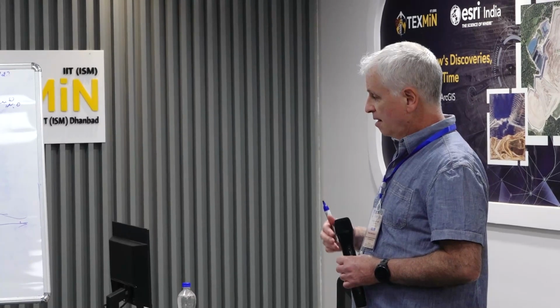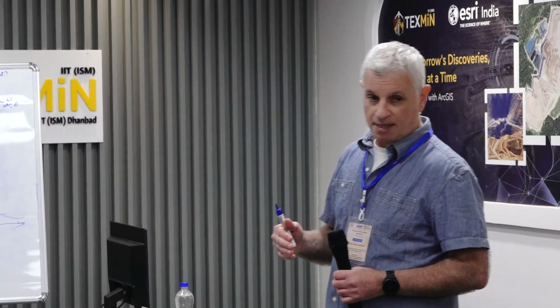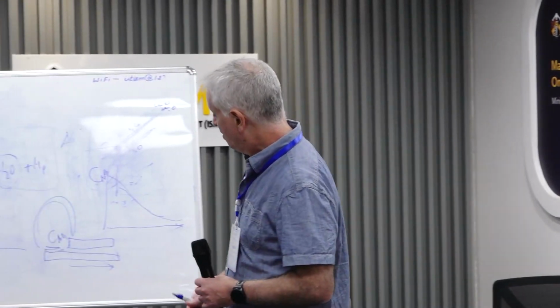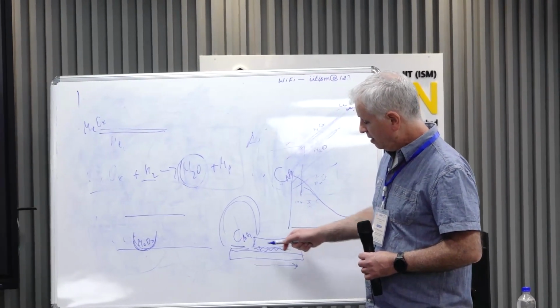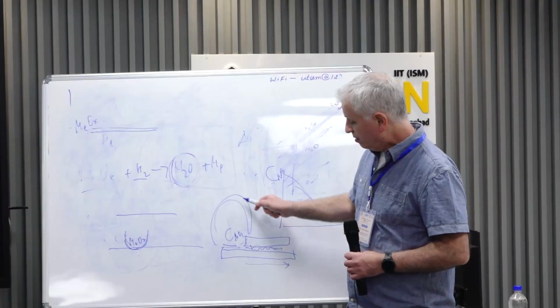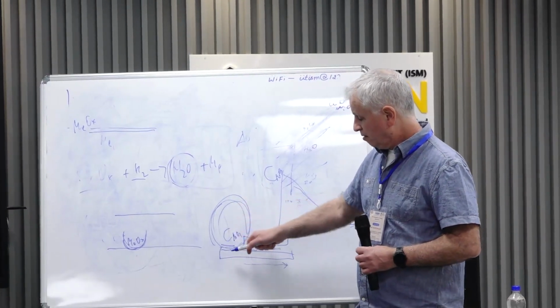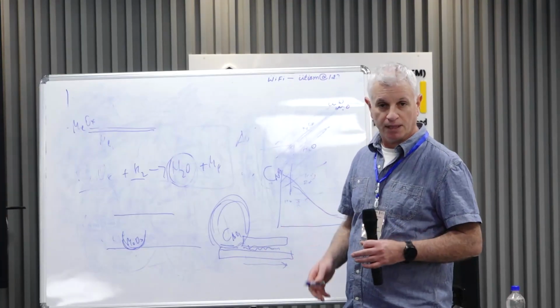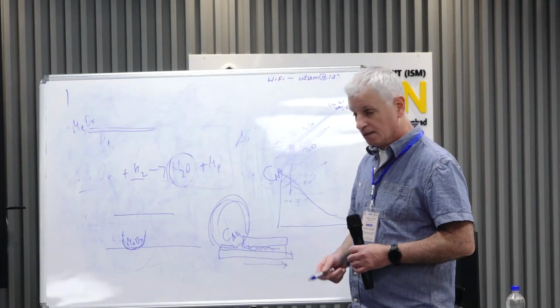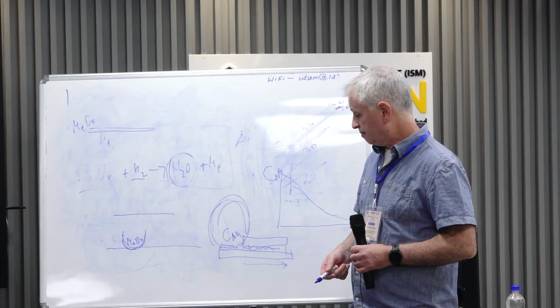Of course, it's not perfect. It took a while to realize, but you can control to some extent the delivery of the precursor to the confined area and avoid the formation of multilayer regions in the important areas. Here, the important area is the confined area.